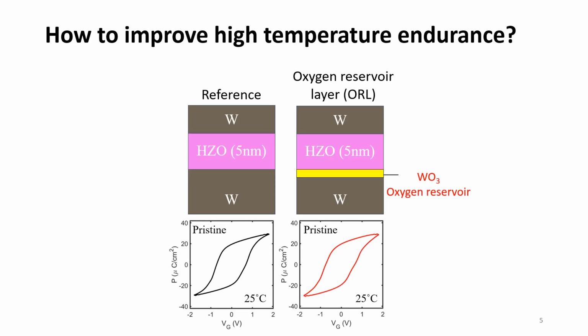And for this study, we have compared this set of devices that you can see here in this slide. So one is the reference device and another is the oxygen reservoir layer device, or the ORL device, which has the tungsten oxide layer at the bottom interface, which will act as oxygen reservoir here. The corresponding PV loops measured at the pristine state at 25 degrees Celsius are shown at the bottom for each device.